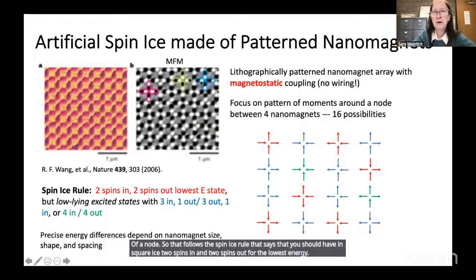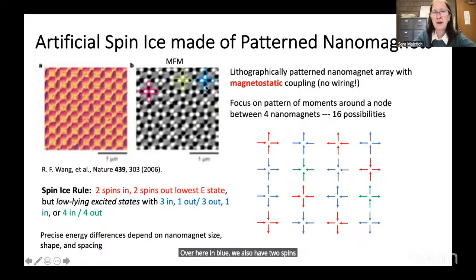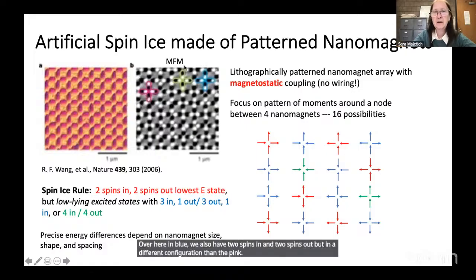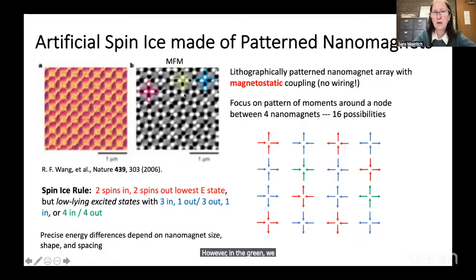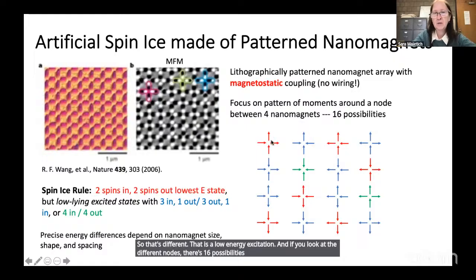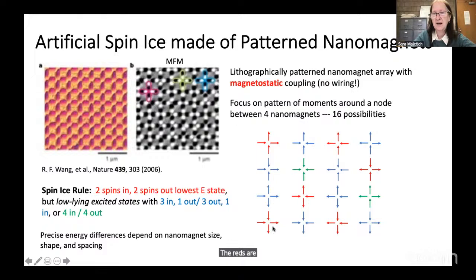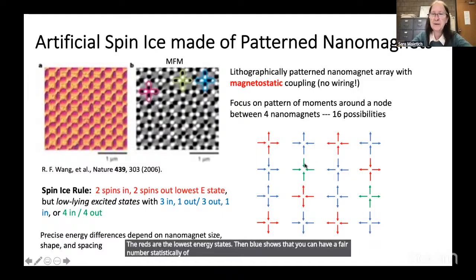Over here in blue, we also have 2 spins in and 2 spins out, but in a different configuration than the pink. However, in the green, we have 3 spins in and 1 spin out. So that's different. That is a low energy excitation. And if you look at the different nodes, there's 16 possibilities for square ice. The reds are the lowest energy states. Then blue shows that you can have a fair number statistically of excited states. And the green are the really excited states with all the spins pointing in or all pointing out.